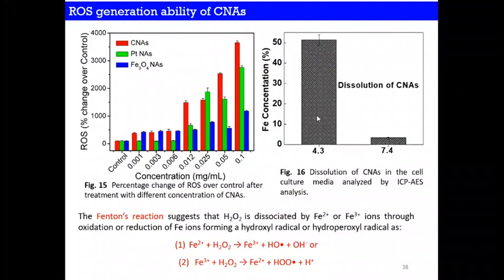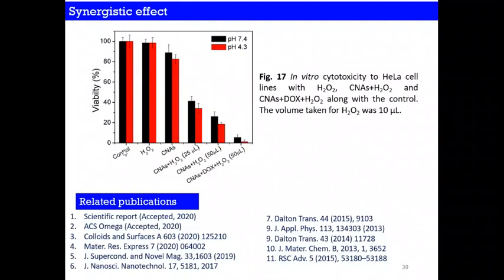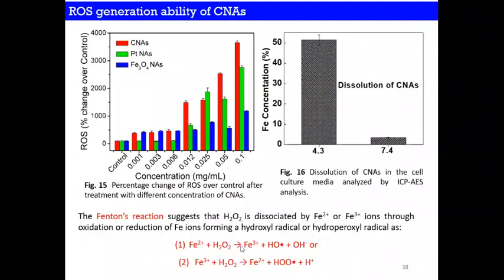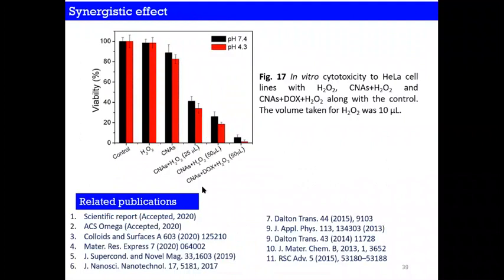This is nothing but the ICP-AES, showing the dissolution of the nanomaterials. So iron concentration at lower pH is very high. So it is releasing a higher iron amount than at 7.4 pH. See here, this is the control one. As I told, hydrogen peroxide, which is there in the mitochondria, decomposes in the presence of iron, and it produces hydroxyl or hydroperoxyl radicals. We manually included 10 microliter of hydrogen peroxide to induce the reactive oxygen species. And it has been found that when DOX along with the nanomaterials and H2O2 has been given, there is complete cell death, and this is controlled cell death.